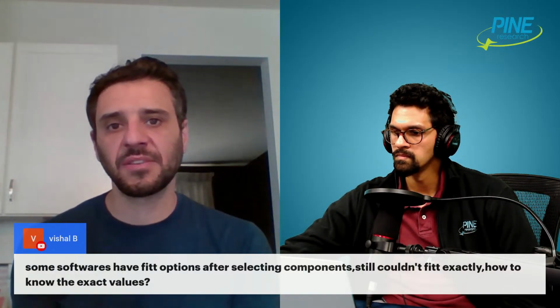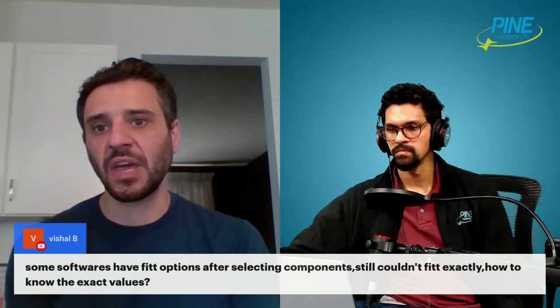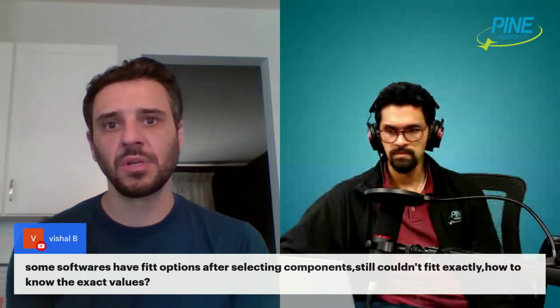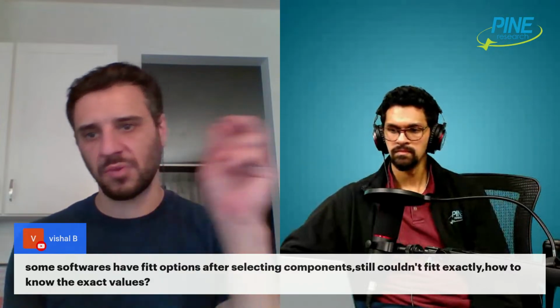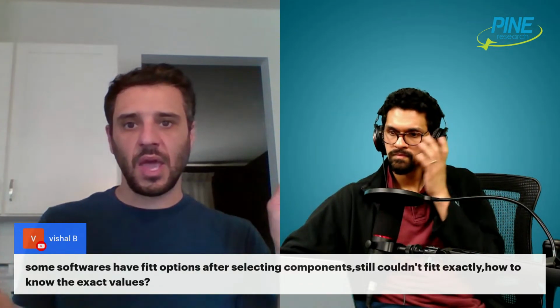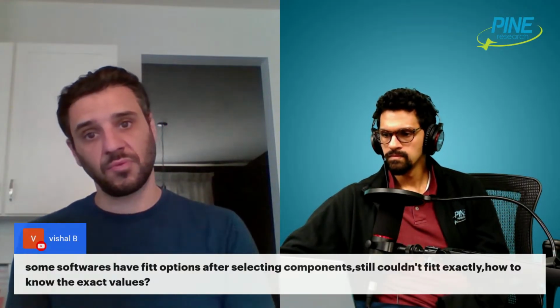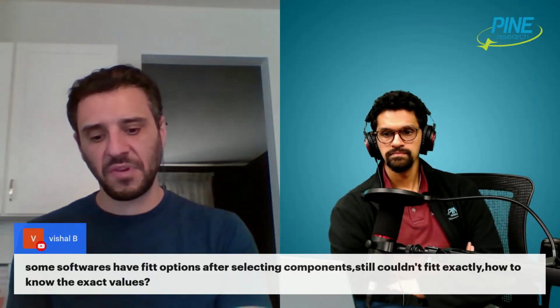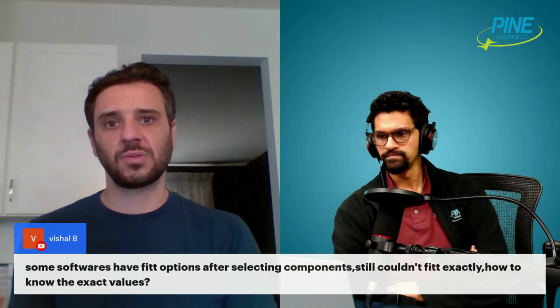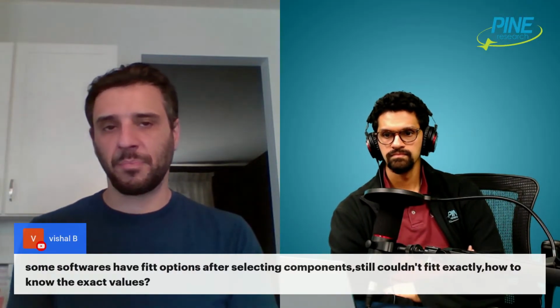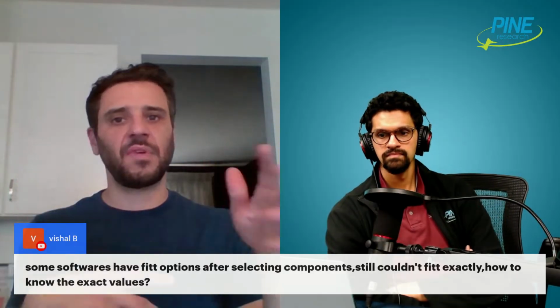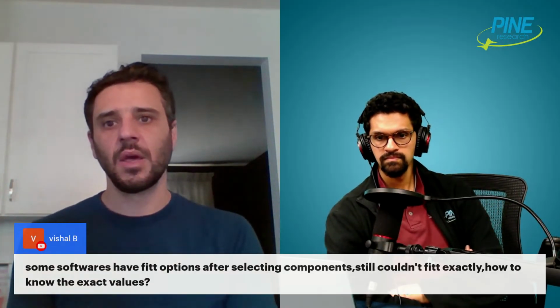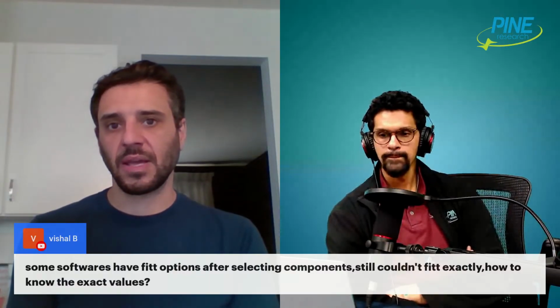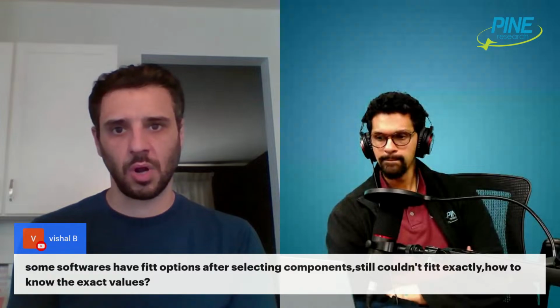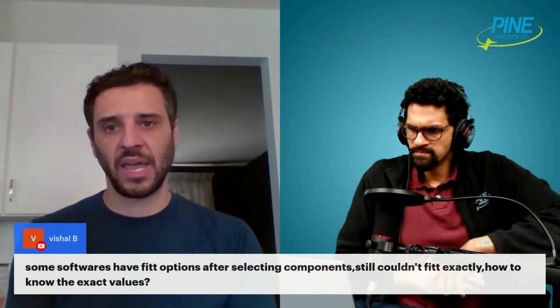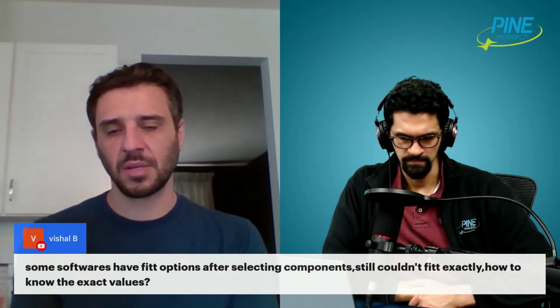But if you do Kramers-Kronig and it doesn't fit perfectly, it doesn't mean you can't do your fit. It just means that in the situation that you've described, you might have picked two RCs, a Randles, whatever I picked, right? And it's not fitting great. Well, I do Kramers-Kronig and it's still not fitting great. Nothing will fit as well as Kramers-Kronig does. Kramers-Kronig is sort of by definition testing the perfect fit. It's not really a circuit fit, but it's kind of like a circuit fit. And so if Kramers-Kronig doesn't fit your data very well, there is no circuit you can draw that will fit it better. As a rule of thumb, I always like to suggest that.